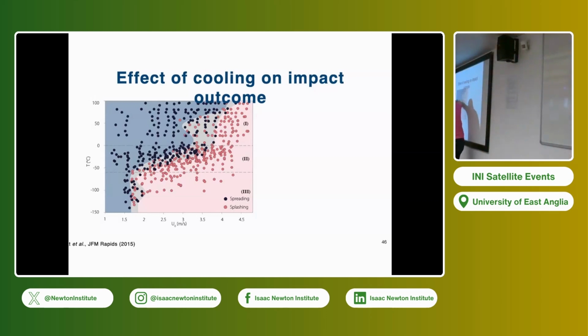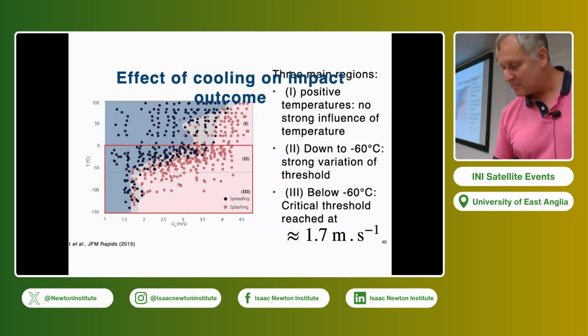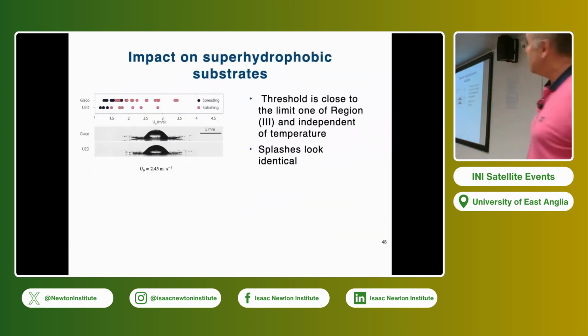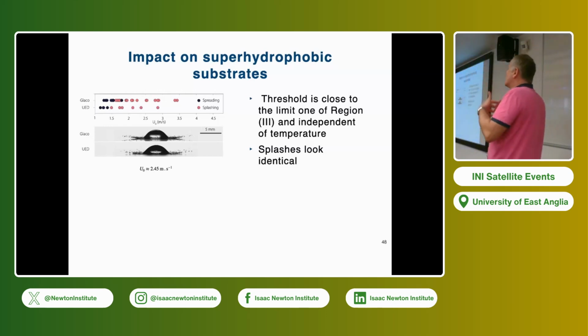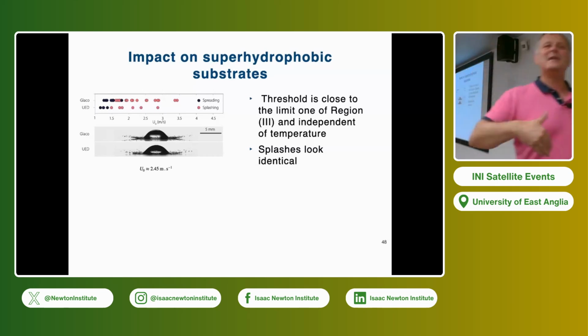To make a long story short, I will just concentrate on why at a very low temperature we have splashing, and what we have is a clue and not an explanation. Let me go fast. If you do the same impact, the same drop, on a superhydrophobic surface, for the same velocity that was spreading at room temperature and splashing at very low temperature, you see splashing. So the conclusion is that a cold substrate behaves like a superhydrophobic surface. The idea is that the substrate does not care about being below zero or above zero; it does not change anything for a metal. On the other hand, the liquid approaching such a surface might have some crystals that grow at the surface, and it might not be the substrate that becomes hydrophobic, but the water that becomes surface-phobic, to make it like a joke.